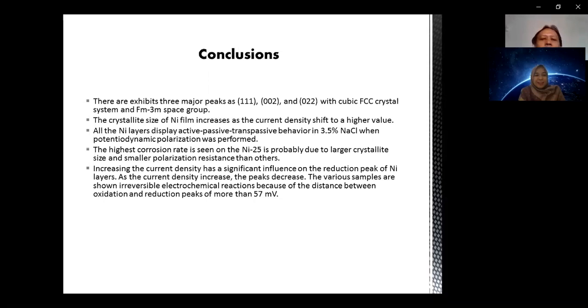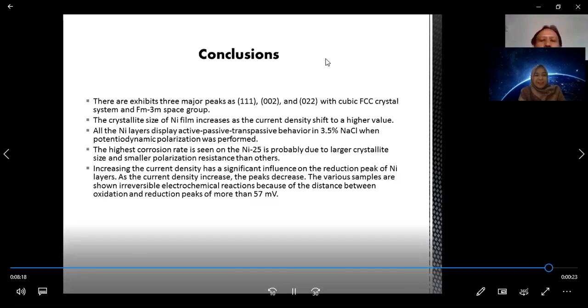Increasing the current density has a significant influence on the reduction peak of the nickel layer. As the current density increases, the peak decreases. The various samples show an irreversible electrochemical reaction because the distance between oxidation and reduction peaks is more than 57. Thank you for your attention.